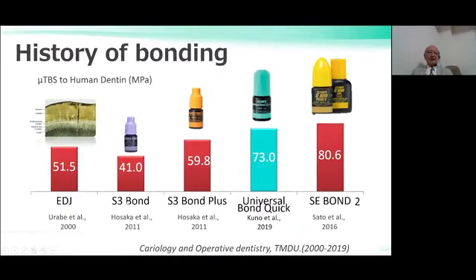Okay, now you can see that these recent adhesive resin materials showed very excellent bonding performance. The recent two-step self-etching material shows a 80 megapascal bonding to dentin. Even with one-step self-etching, one kind of universal bond, more than 70 megapascal. This is strong enough in the clinical use. However, if we know that this is better, I'm very happy to use it.